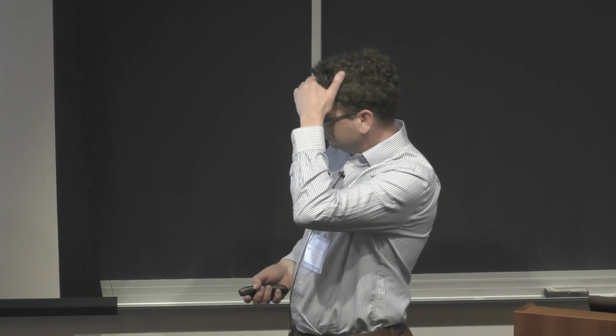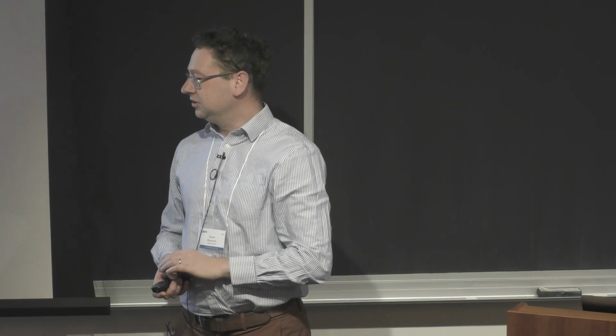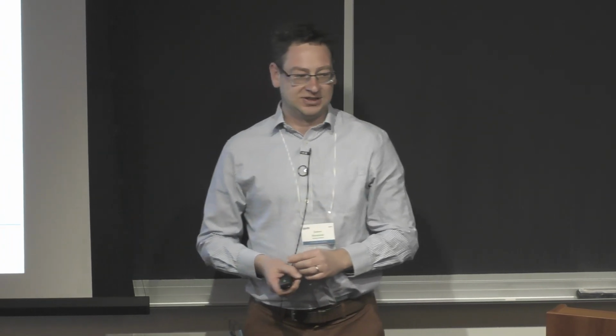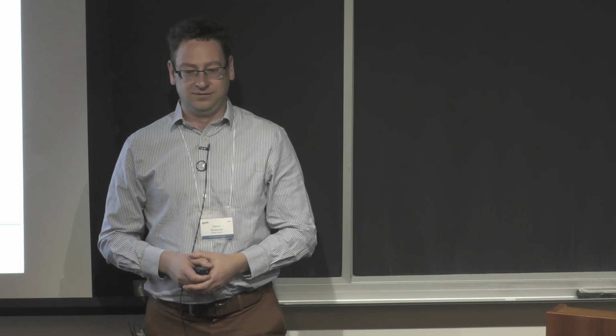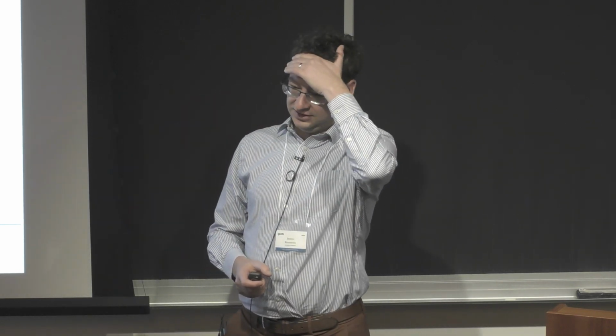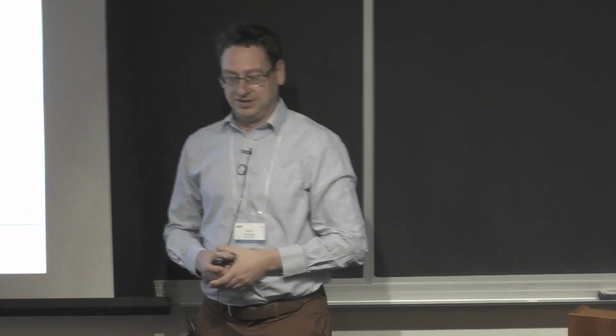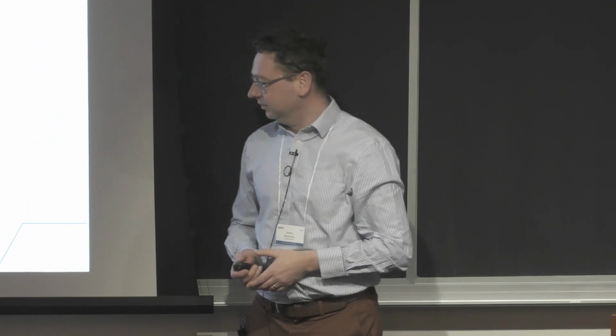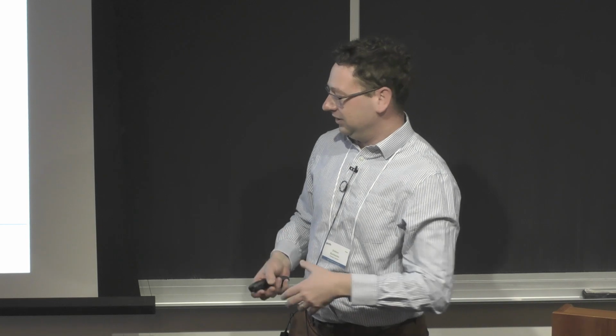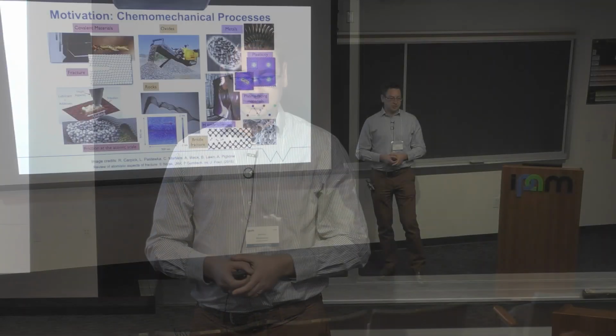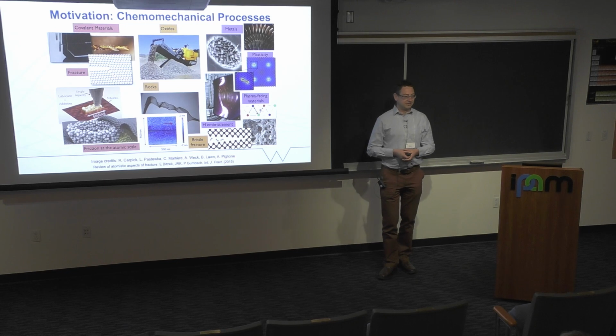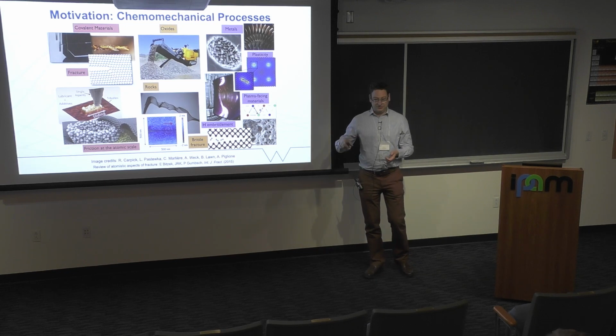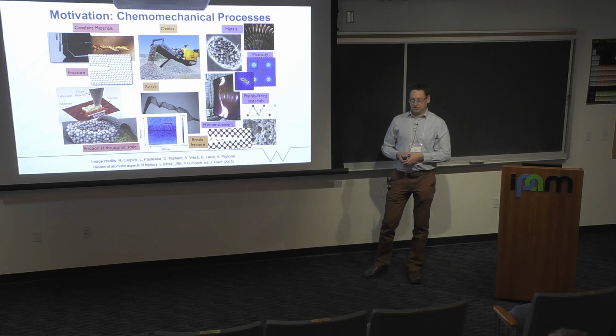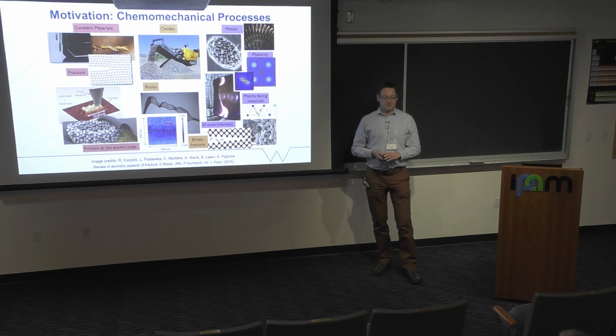Another example is plasma-facing materials for nuclear power stations. There we need materials which can withstand the immense flux of heat and energy that you get from a reactor core. Tungsten is the only material that's up to the job, but there's a lot to understand about how it interacts with hydrogen and helium, for example. Another prominent example that inescapably involves chemistry would be hydrogen embrittlement. So we've got a nanoscale crack tip in something like iron. Hydrogen is diffusing around inside the material, getting to crack tips and causing stress corrosion fracture or subcritical crack growth. And so we can't really avoid the need to describe chemistry at the same time as mechanics.